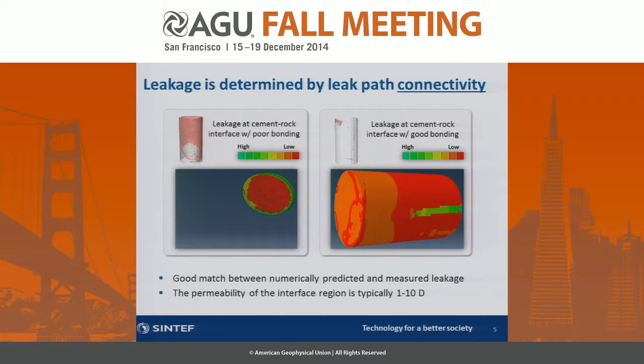But we see that in the case of a very well-bonded rock, then you also have areas where you have very, very little leakage. So what we found is that even very small, well-bonded areas of cement can be a very efficient barrier towards leakage. While when you have a lot of interface porosity, then of course this has a very high porosity.